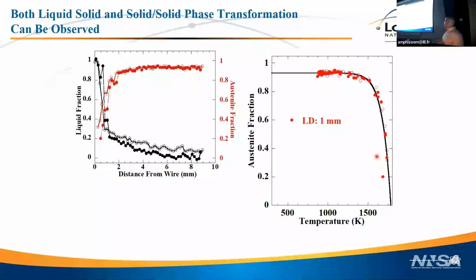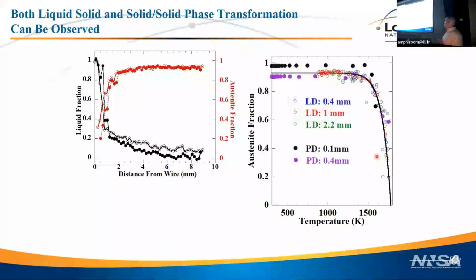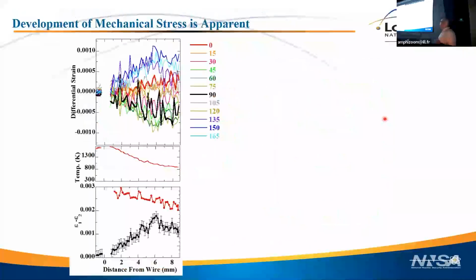So these are the line depositions, all the line depositions at different heights above the substrate. If I take that back to the point depositions that we did, you see that it all agrees very well, but remember the point deposition, we had very poor time resolution. We only got one point on each of those while it was cooling, so it wasn't so satisfactory. And this can be fit, I just empirically made up an equation that fits that quite well. I have no theoretical basis for that equation.